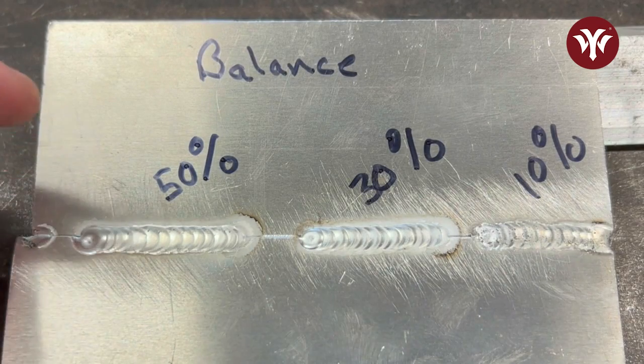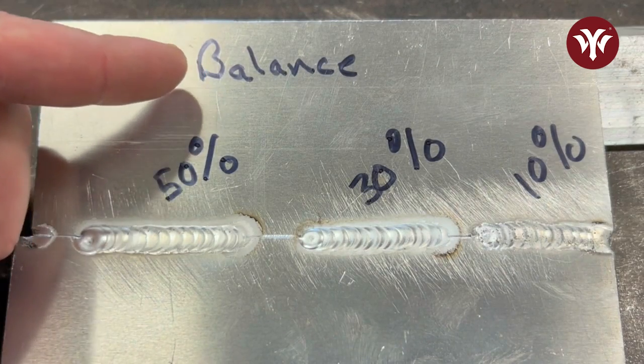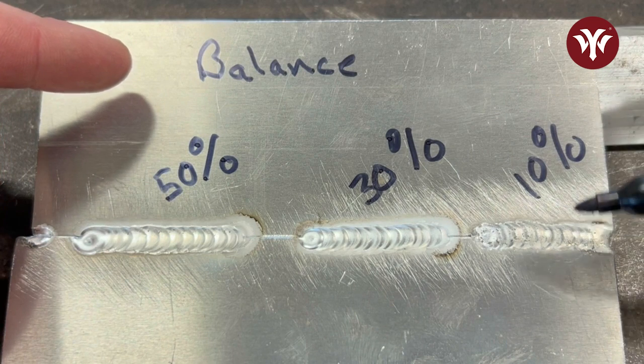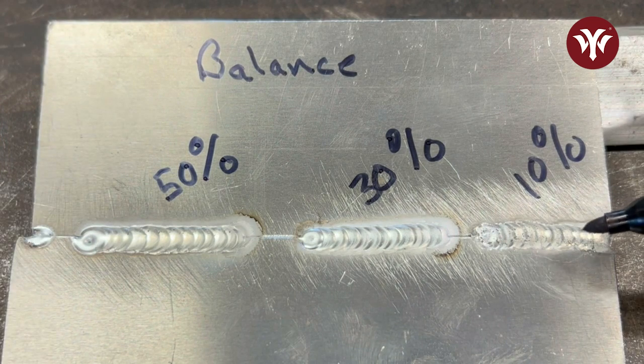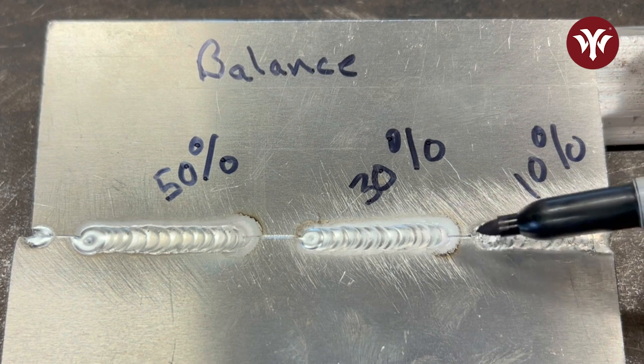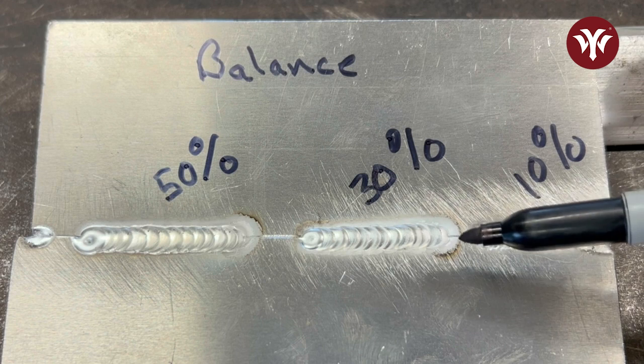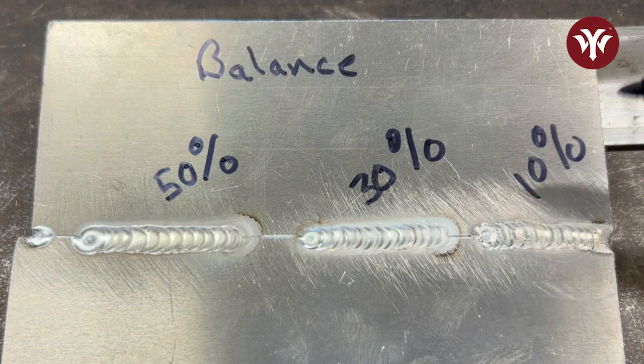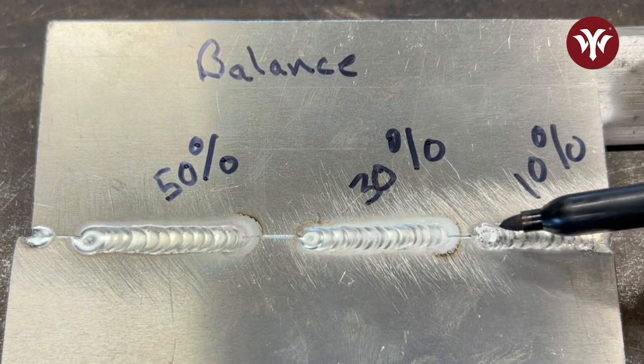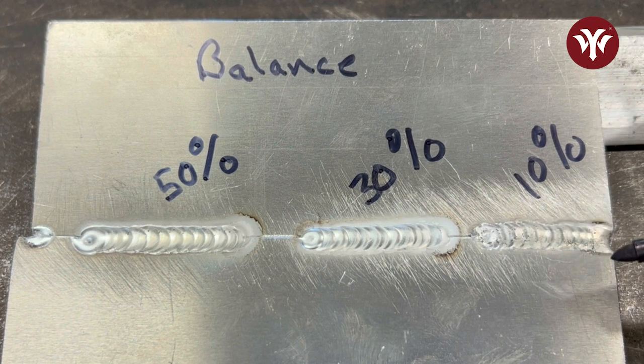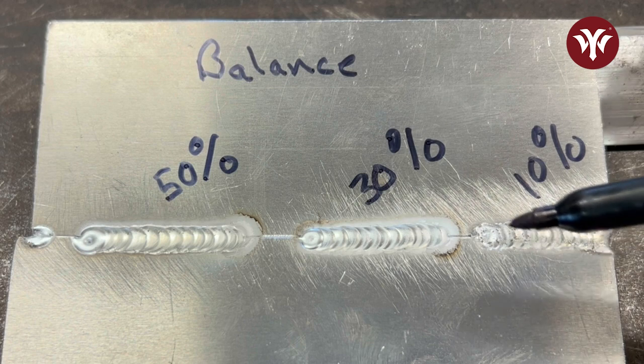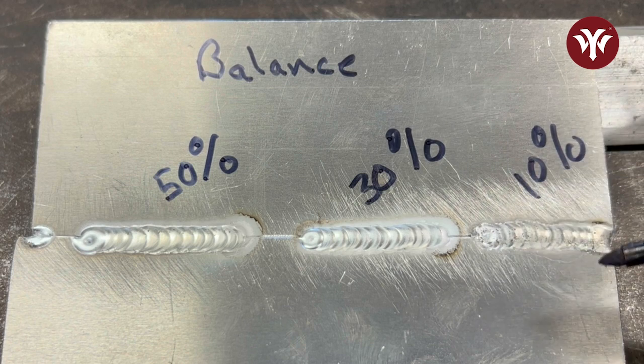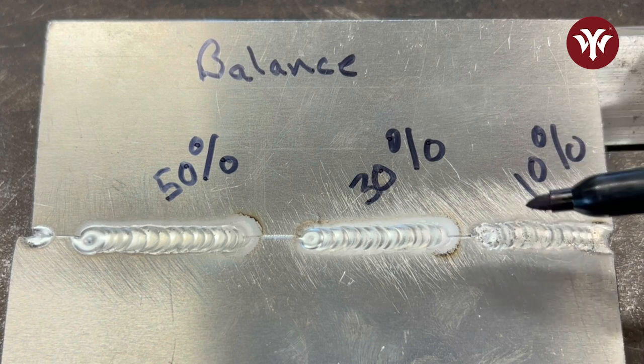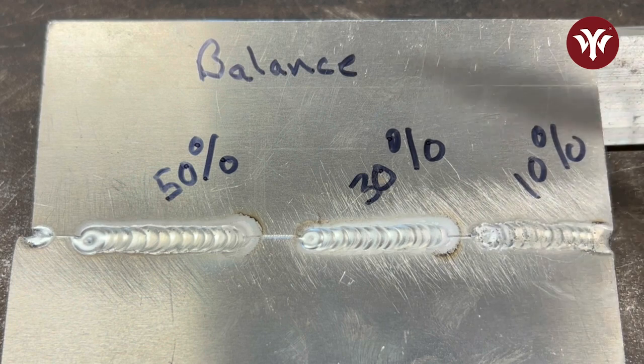All right, now that we got that first test done with the balance, let's take a look at the results here. As you can see, we're running with 10% balance, and that is not what I would be looking for. The etching zone around the weld is almost non-existent, which happens from cleaning, the positive half cycle. There's a lot of contaminants on top of the weld puddle itself, because they weren't getting removed, they were merely just floating up to the surface. So 10% with this material is too low for my liking.